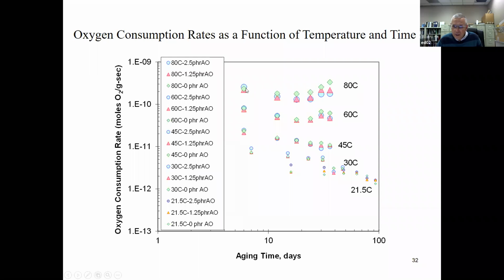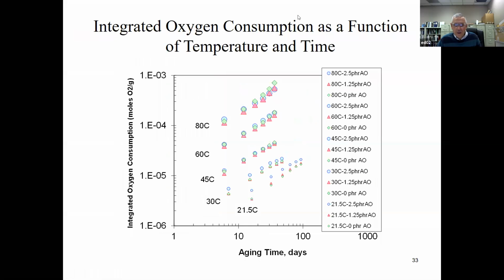So it seems like there's a mechanism shift, right? When you go from 80 degrees to 21 degrees, in the middle they're kind of oxidizing at the same rate. So there's kind of a shift. And then here we show the integrated oxygen consumption again. At 80 degrees C, the compound with no antioxidant is aging faster, oxidizing faster than the one with antioxidant, the expected ranking. But at low temperature, we're seeing the opposite, where the one with 2.5 pHr of antioxidant, the blue circles, is oxidizing faster than the compound with no antioxidant.